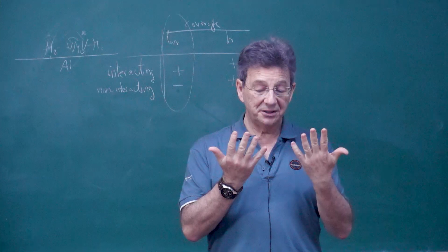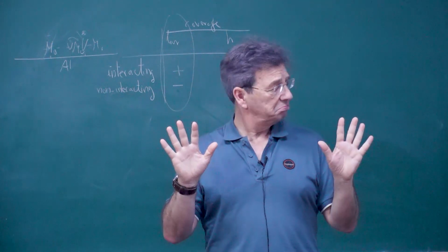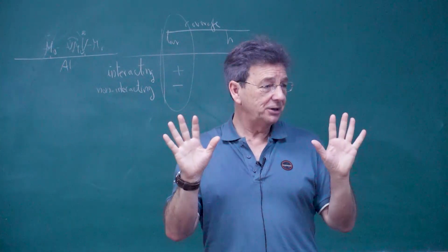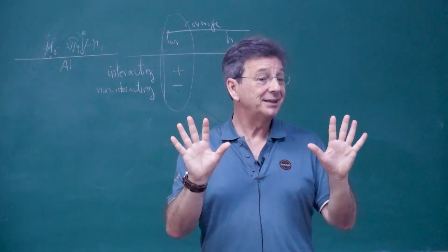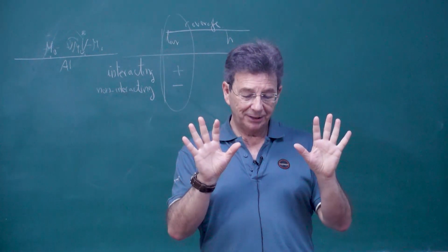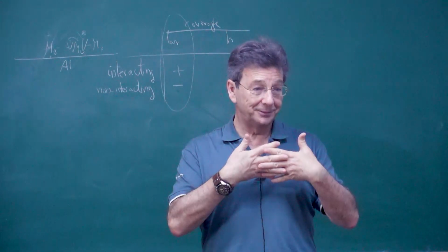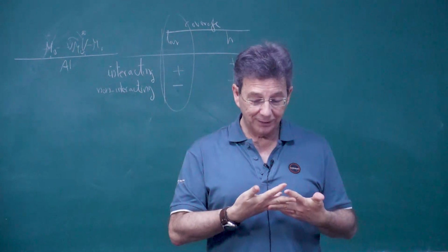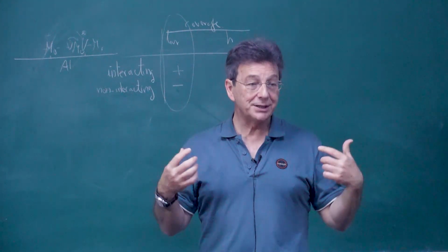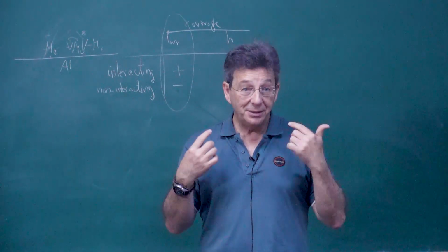So the interesting thing is this dispersed vanadium and that dispersed antimony, even if you make calcination at 1 monolayer, they just, okay, hi, hello, but they don't really interact. They only say hello because they are very polite elements, that's it. But then when you are doing catalysis, something is happening, and somehow they blend, they combine into something. And then you start to get the vanadium antimonate. So the reaction is actually the driving force to make the mixed phase.